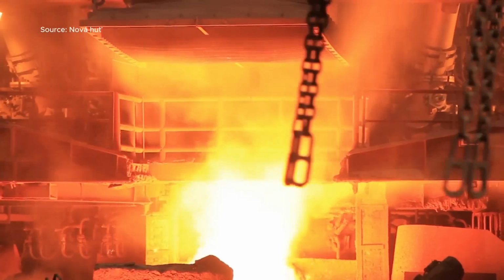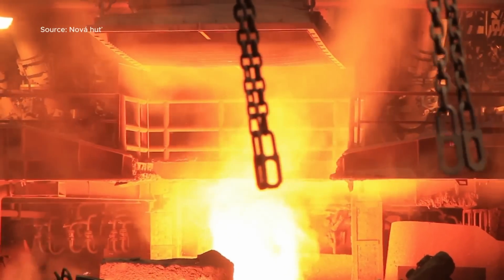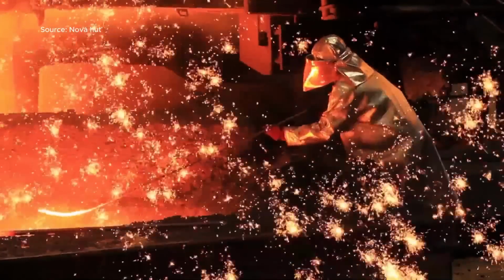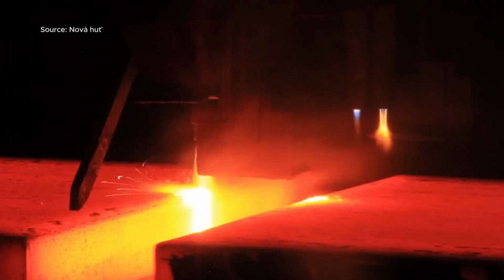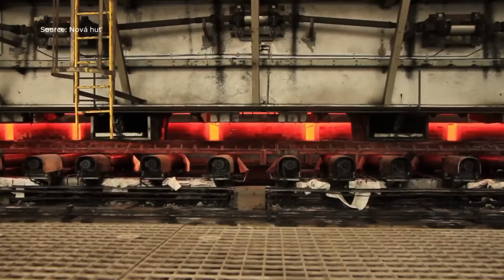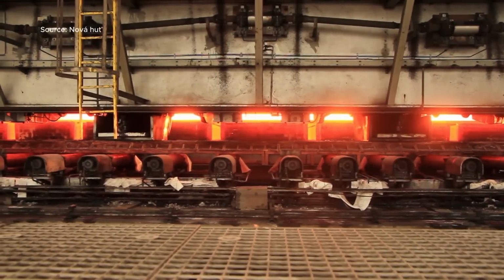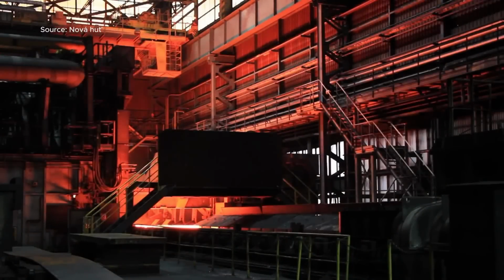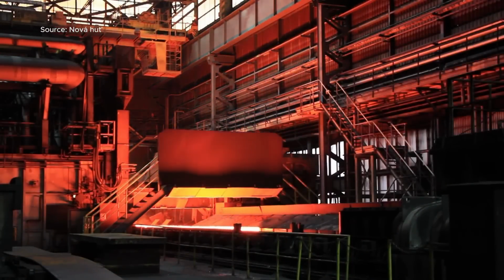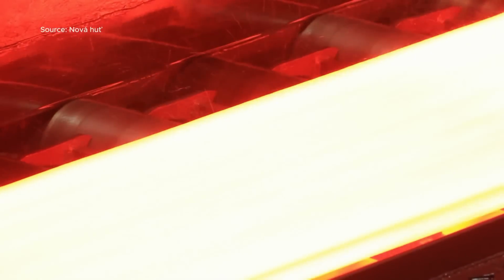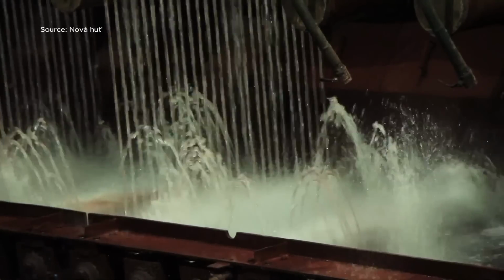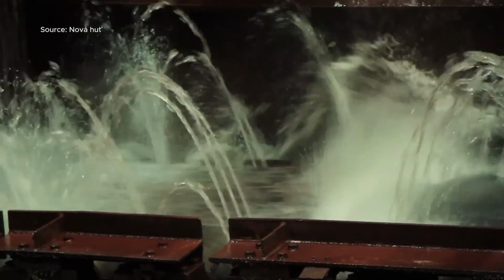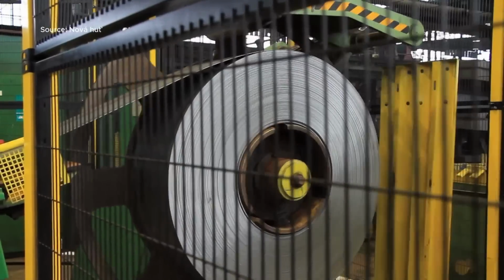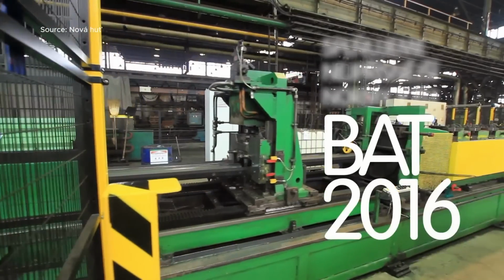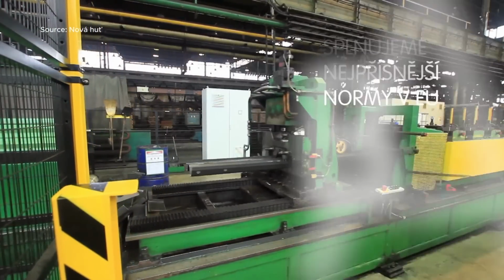It begins with steel slabs heated beyond 1,200 degrees Celsius, rolled and quenched by high-pressure water jets. The cooled strips are then fed into forming lines, shaped into W-beam guardrails by a series of rollers. Mounting holes are punched and sections are cut to length. Hot dip galvanizing adds corrosion resistance. Final checks verify strength and dimensions.